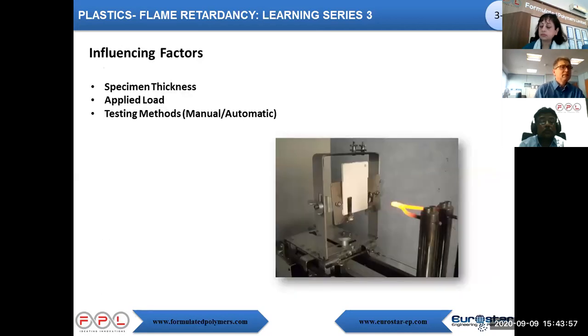Okay, the influencing factors. Here you see the test we have in FOS. You see the wire, which is very heated. It should be 960, because around 850 is red, but around 950 is almost white or very yellow. In principle, this sample holder is moving toward the rod, the burner, and you are measuring the interaction.